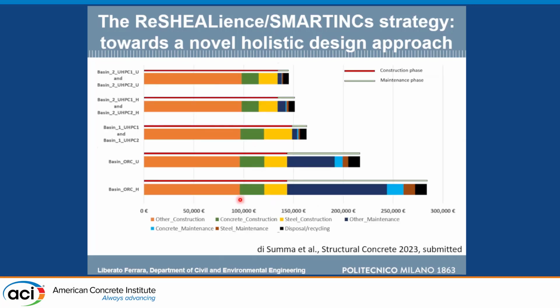And when you come to costs, you see that the construction costs for ordinary reinforced concrete are absolutely comparable to the UHPC ones. It's true that the material costs more per cubic meter, but it's also true that you use half of it, 30% of it. So this makes the construction cost comparable. The huge saving that you have is that you do not have almost any significant maintenance cost, very limited, just to keep the structure functioning, and you do not have to intervene.